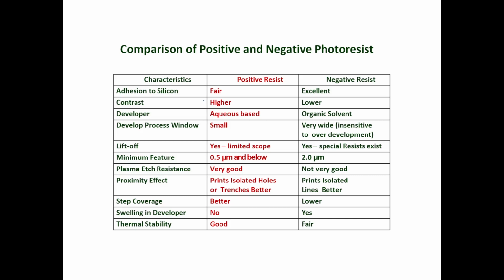Lift-off process we can use, but with negative photoresist it is easy. Minimum feature size is 0.5 micrometer and below. If you want to develop a device with a size of 0.5 micrometers or in nanometers, you can use positive photoresist, and for 2 micrometers or above you can use negative photoresist. Plasma etch resistance: oxygen plasma is very good. If any positive photoresist remains after developing, you can remove it through plasma etching, but negative you cannot remove that way. Step coverage means that if you make some step, it will cover very well, but in the case of negative resist you do not get it right.